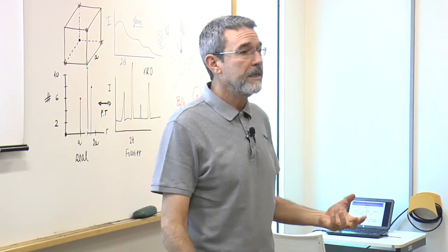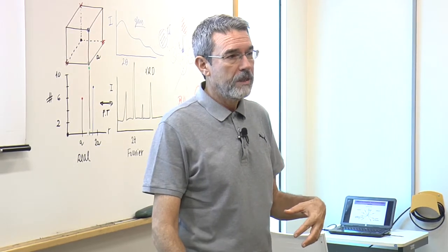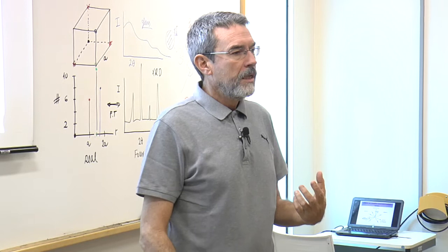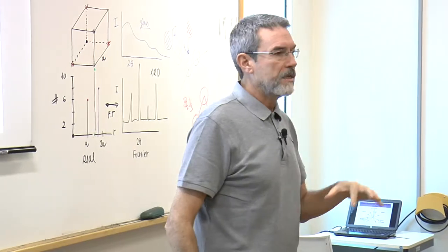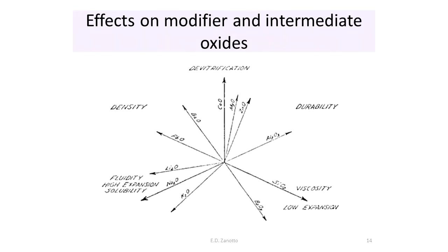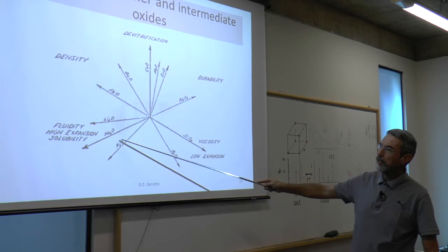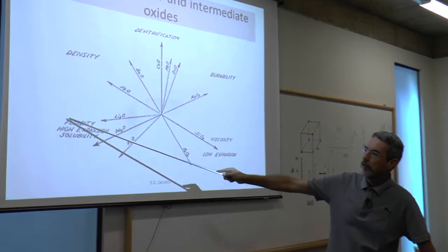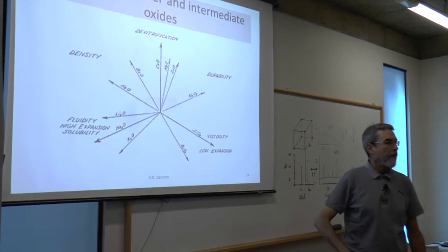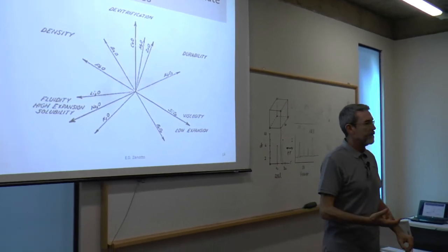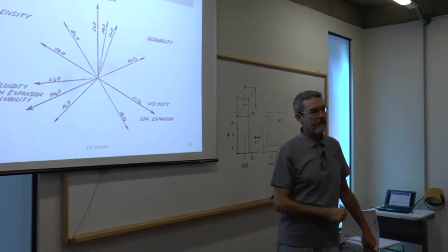P2O5 is easy to make, but the chemical durability is very low. B2O3 is very easy to make, but the chemical durability is very low. So, in glass technology, in very rare occasions, we use pure oxides. We normally add certain elements, such as, for instance, lithium, sodium oxide, or potassium oxide, to help us to make the glass, to melt at lower temperature, for instance.